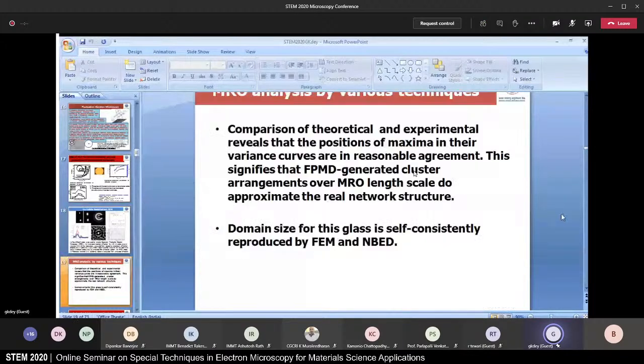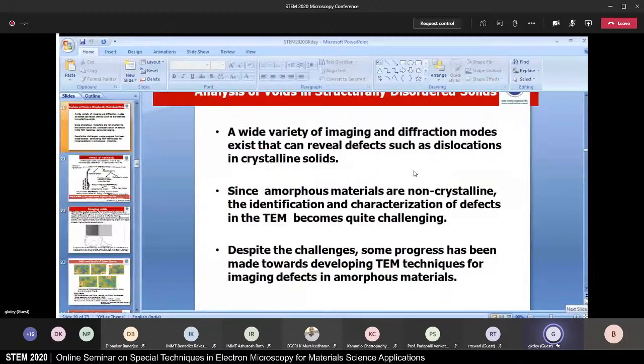Just to conclude the medium range order part, comparison of theoretical and experimental results reveals that the positions of maxima in the variance curves are in reasonable agreement. This signifies that the FPMD generated cluster arrangements over the MRO length scale do approximate the real network structure. The domain size for this glass is self-consistently reproduced by FEM and NBED. The last part to be determined is the void.